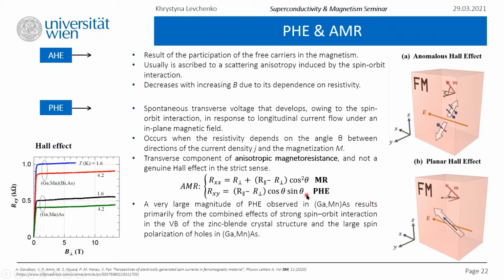In other words, planar Hall effect is developed when the spontaneous transverse voltage is created due to the spin-orbit interaction in response to longitudinal current flow under in-plane magnetic field, or sometimes even in the absence of the magnetic field. Planar Hall effect is a transverse component of the anisotropic magnetoresistance, a larger phenomenon. So AMR usually occurs in ferromagnets and is a magnetic field-dependent response of the carriers, resulting in a change of electrical resistance. Here you may see two equations that are usually used to describe a single domain model, the longitudinal component and the transverse component.